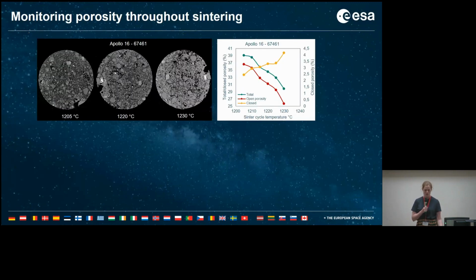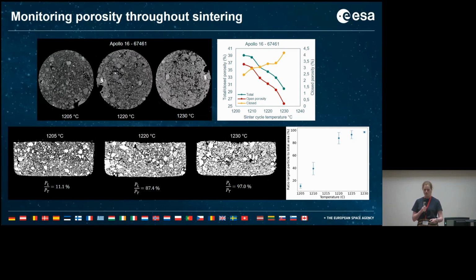And so this is just quickly to show that we're monitoring the porosity throughout the sintering process. So we can see the porosity as it changes with temperature, and looking at other methods of monitoring the degree of sintering as well. Like, for example, looking at the proportion of the particles that are joined together using image analysis.